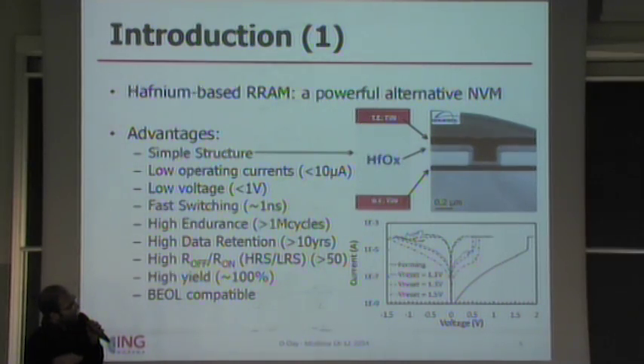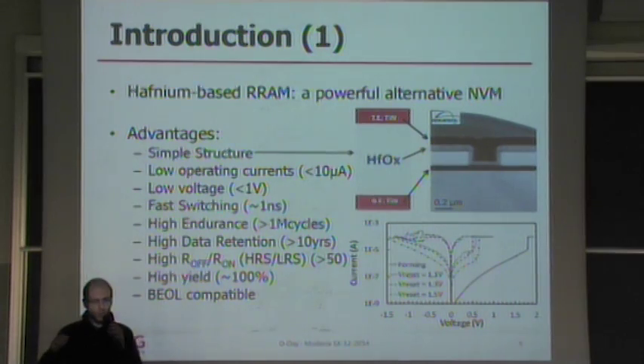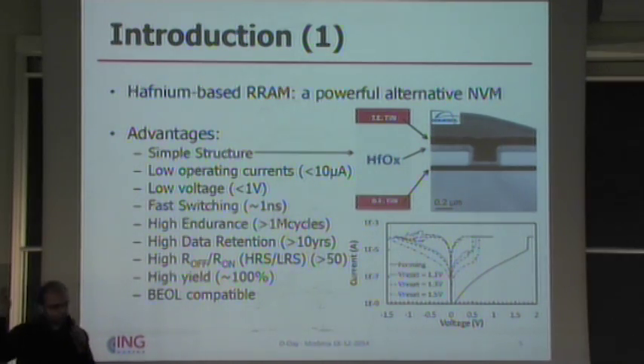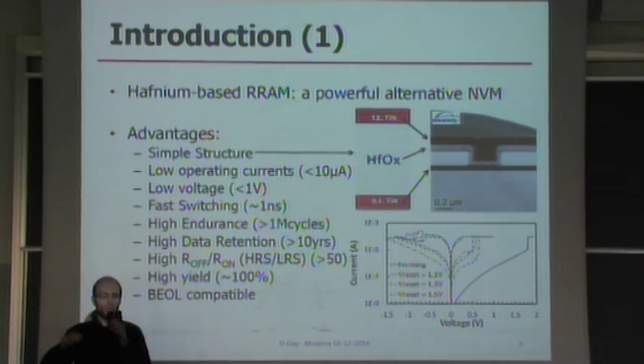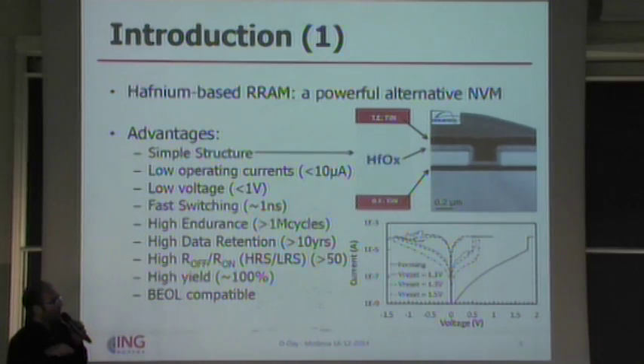But actually, we can break it down. If we apply a voltage ramp, we can break the device down. However, if we control this breakdown by imposing a current compliance, as you see over here, then we are not really destroying this device, but we are kind of building a conductive path, a conductive filament in this structure. And if we are good enough in controlling this breakdown, now this breakdown comes to be reversible.